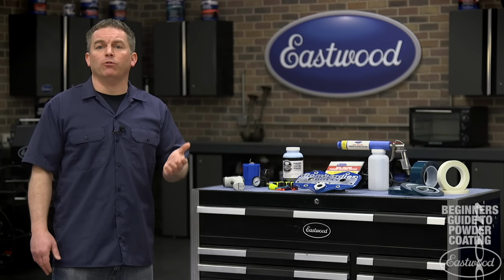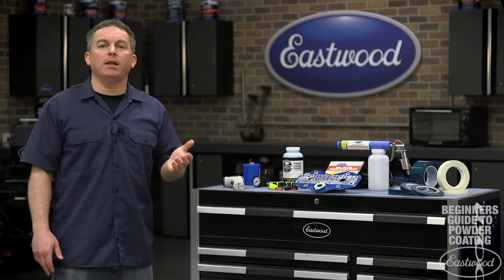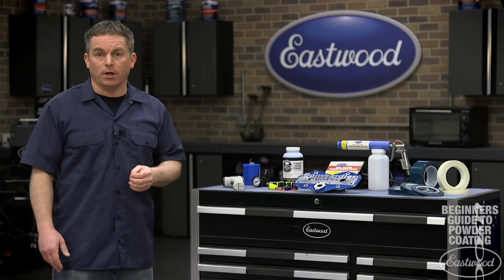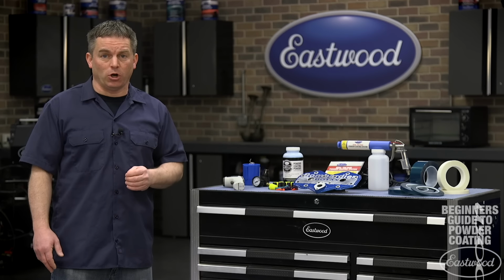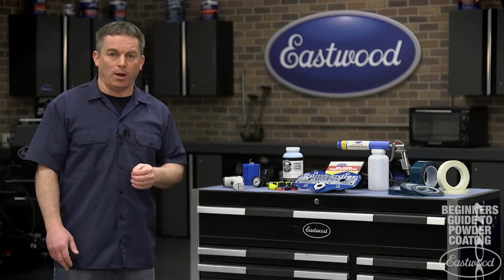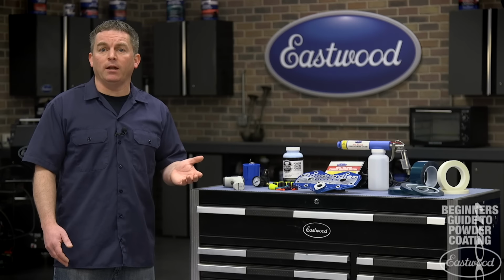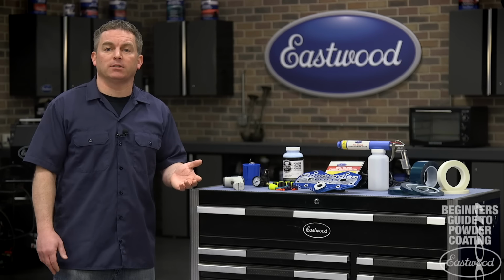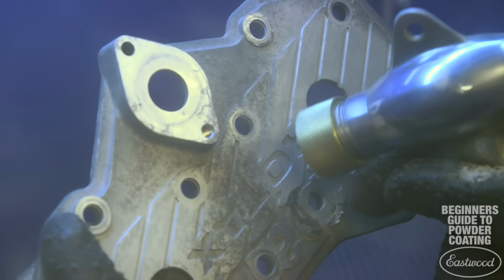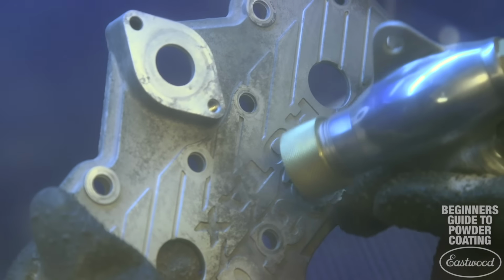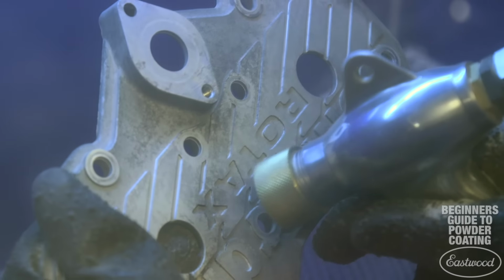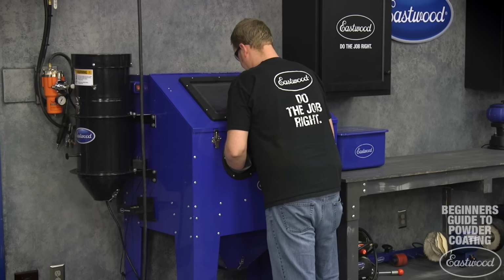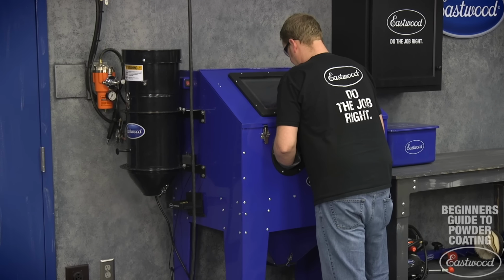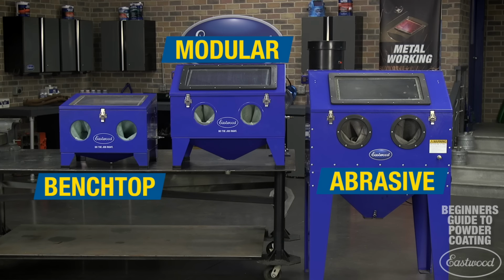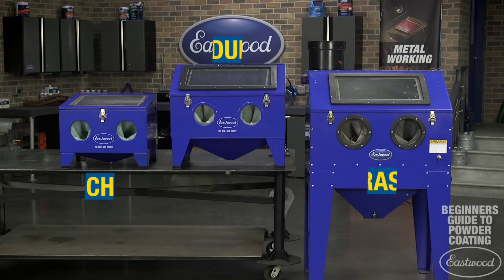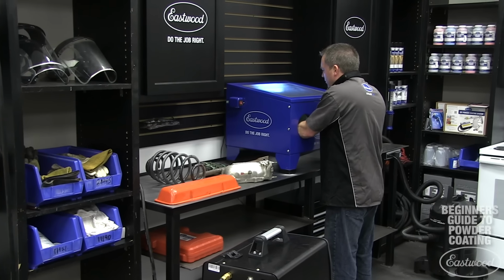You will also need to remove any old coatings like paint, since many paints won't withstand the curing temperature. Paints will also not conduct a charge, which means the powder won't adhere properly. A great way to remove paint and prep the part for powder is by blasting, in a cabinet or with a pressure blaster. We put the head cover in the Eastwood blast cabinet and use glass beads to fully clean the part. We used our large cabinet, but if you're only doing small parts, Eastwood offers other sizes of cabinets, including a benchtop version that's great for small parts or even crafts.